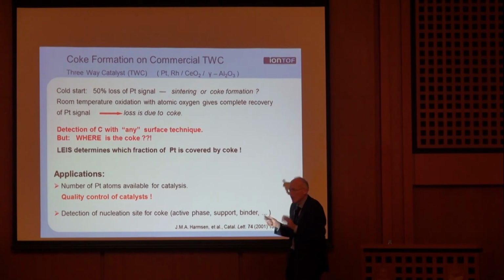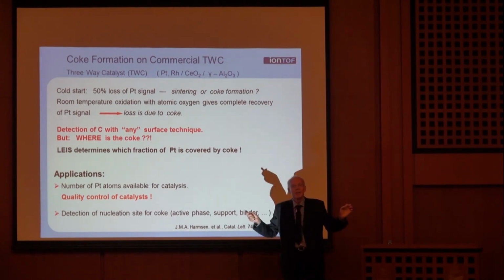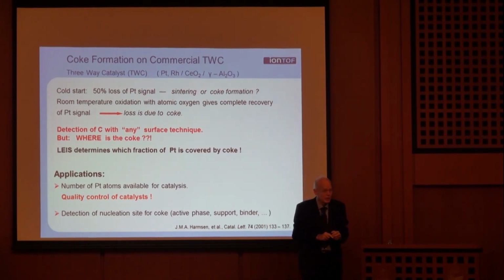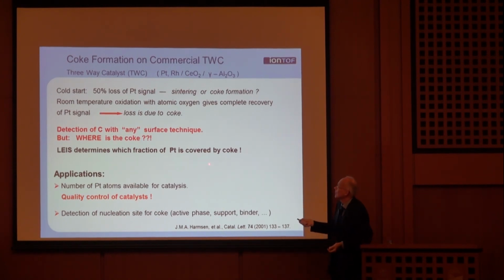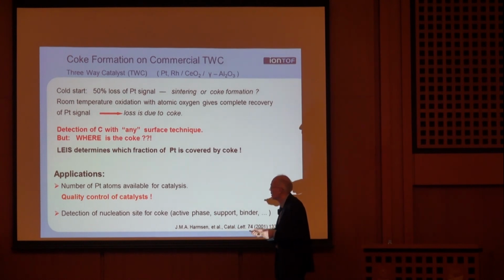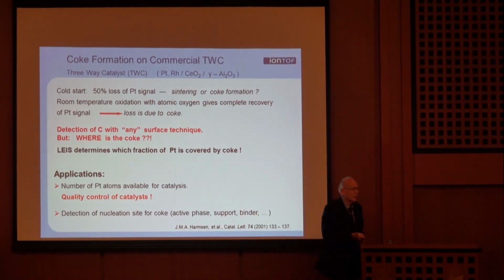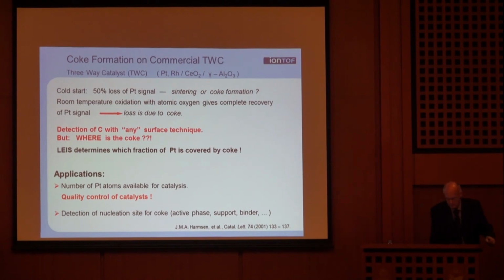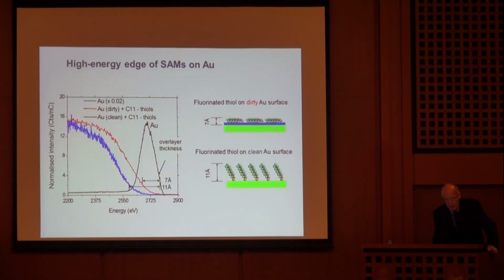And so by looking at how your signal depends on coke formation, which elements disappear, you know where it goes. And if you don't believe it, at the end, you treat it with atomic oxygen at room temperature, and then the signals come back again. So this is a way to learn about nucleation of coke. And we do that a lot for exhaust catalyst and other things. If I go back just a second.